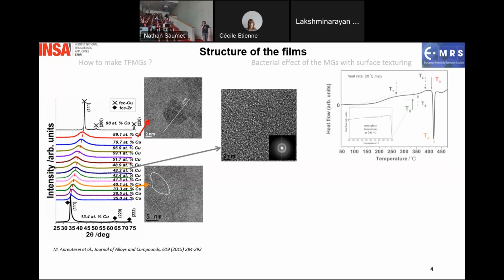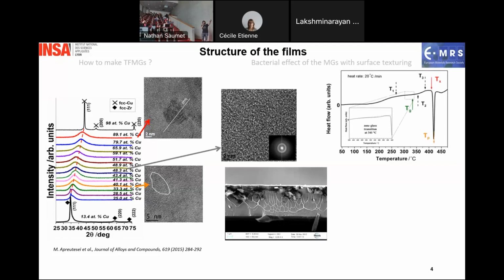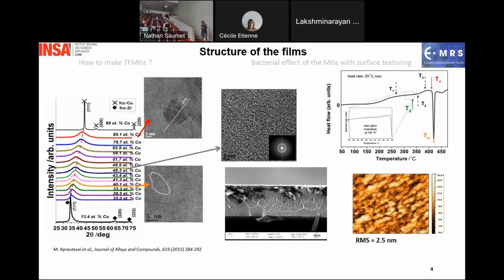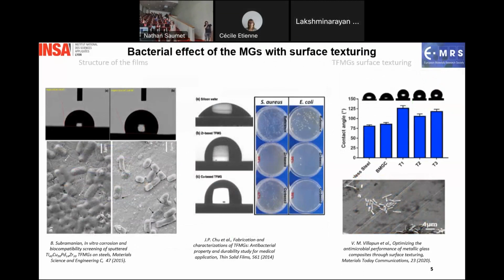Another way to check the metallic glass properties is to check the glass transition, here near 300 degrees. Also, when we cut the thin layers, we see this vein-like pattern, which is very particular to metallic glasses. An interesting property of these metallic glasses is their very low surface roughness, about 2.5 nanometers just after the deposition process. It is well known that metallic glasses can have some bacteriological properties linked to the wettability of the surface and the surface structuring.